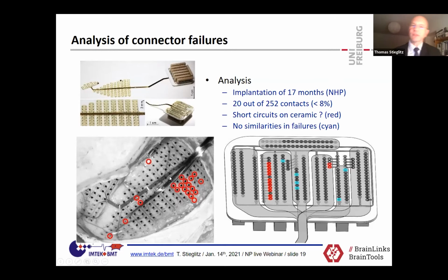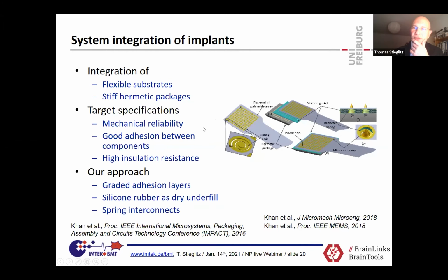And what material could you use? All materials I know were not the best ones. And then we came to the idea, why not put silicone rubber in between? It's flexible on one hand, so if you wiggle, it can be just a little bit pressed or pulled, and it's not that permeable to ions. So that means even if we have water there, it's more or less deionized water, and should have a good insulation resistance. And this slide is for the freaks of micromachining who might be here.